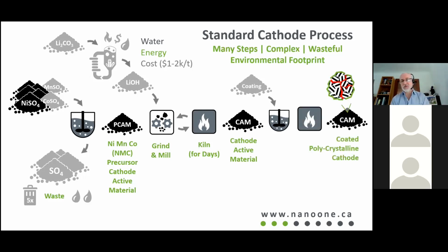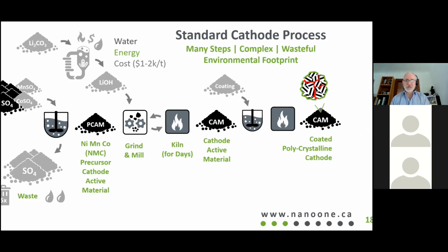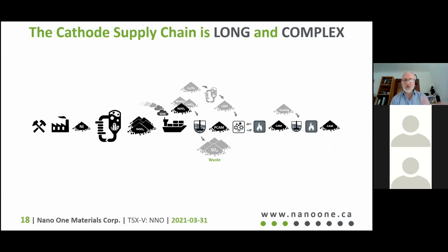And you go, okay, I've got my cathode active material, but then you have to add the coating. And when you add the coating material, you then have to fire it again to finally get your coated polycrystalline cathode, which, as I explained earlier, the coating doesn't last very long because of the expansion and contraction of the particles. So you've got this hugely long, complicated supply chain, and Nano One looked at this and said there has to be a better way of doing it.